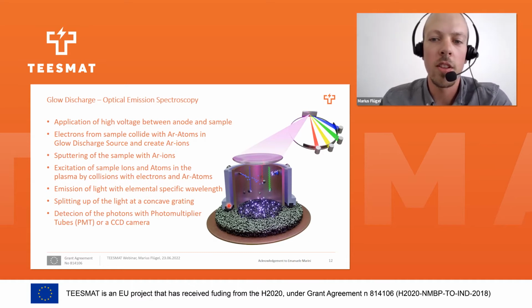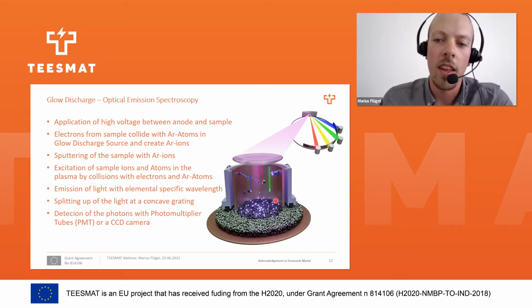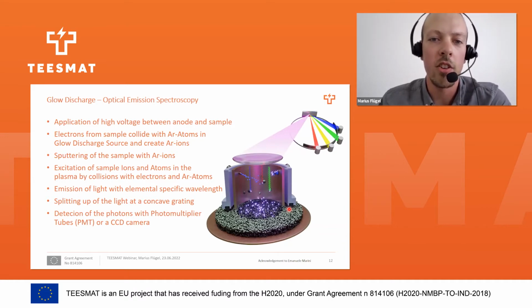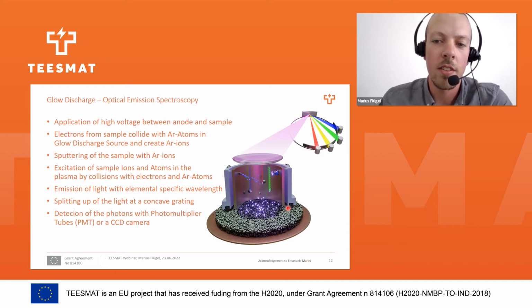After that, a high voltage of 500 to 1000 volt is applied between the anode and the sample. Those are not in contact, so by the high voltage, electrons from the sample surface are accelerated towards the anode, and due to their high speed, they ionize argon atoms during the collisions. The argon ions are then accelerated towards the sample surface due to a positive charge, and when they hit the sample surface, they sputter off sample atoms.